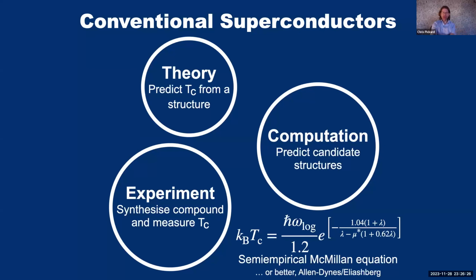So I'm going to leave unconventional superconductivity and the cuprates to one side for the time being, but point out that with techniques like random structure searching and other structure prediction techniques, we can explore theoretically the range of possible structures that might exist. And with a parallel development, which I can take no credit for, but particularly built around the Quantum Espresso computer code, it's become possible, from a given structure, to compute the superconducting transition temperature using various approximate methods, but largely involving computing phonons and electron-phonon coupling